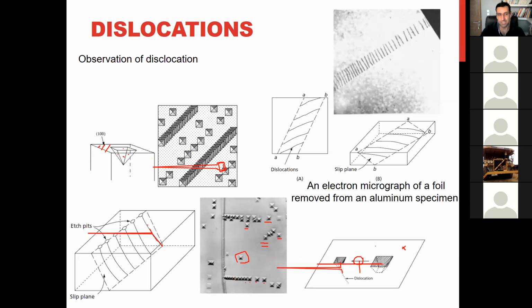So these dislocations come to the surface, and the pit shape depends on the plane we have here. We can see these pits, which are dislocations. This is the case of 111. If this plane is 111 itself, these become like a triangle, like this. We call them etch pits. This is the first observation of dislocation that we can understand. Inside a single crystal, we have some defects; we call them dislocations.